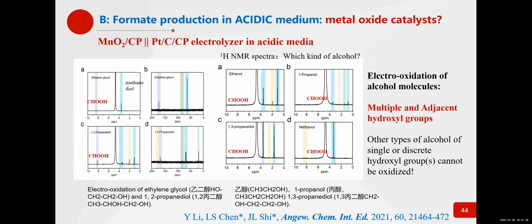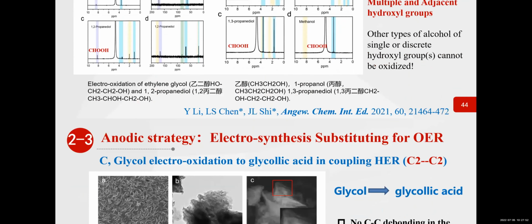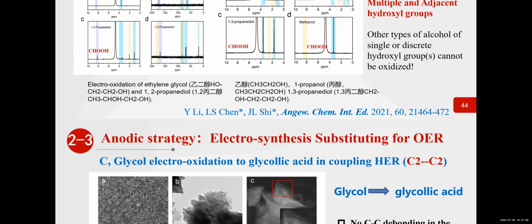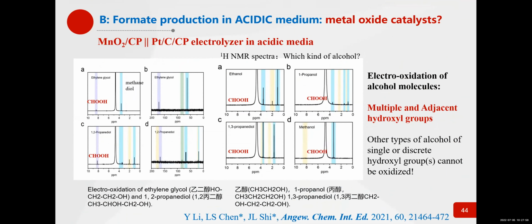And we found what kind of organic molecules can be used to protect the manganese oxide catalysis. We found that alcohol molecules with multiple and adjacent hydroxyl groups can be used to protect the catalysis without dissolution in acidic medium. And we also found that several other kinds of alcohol molecules with multiple and adjacent hydroxyl groups are usable in this kind of electrocatalytic process for the HER and for the formate production. Other kinds of alcohol molecules are not functional, not usable in this kind of system.